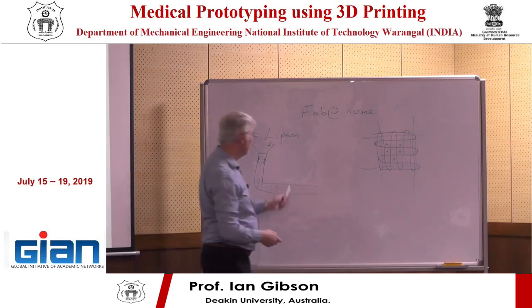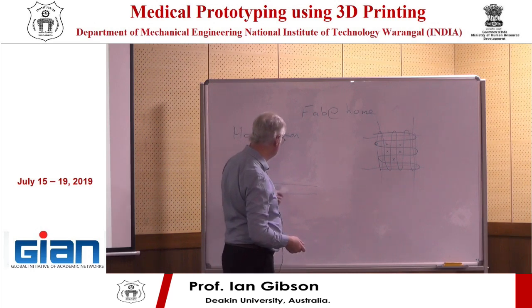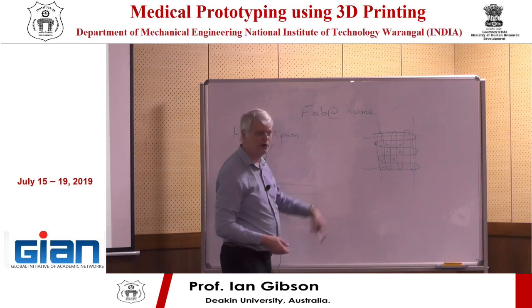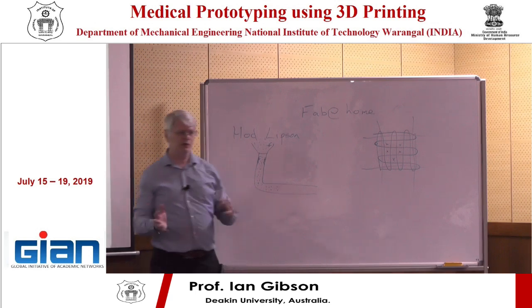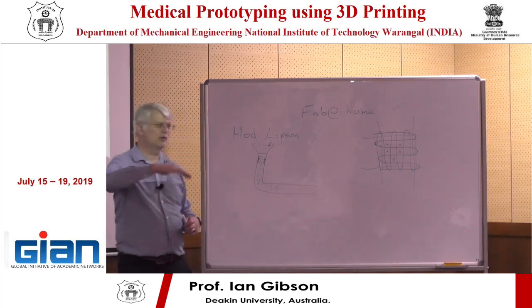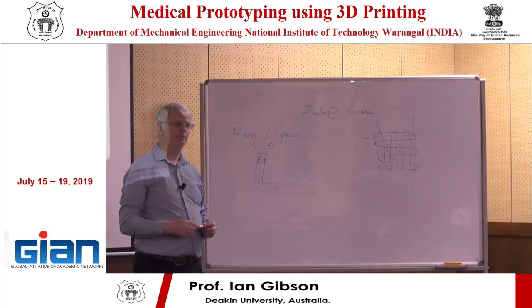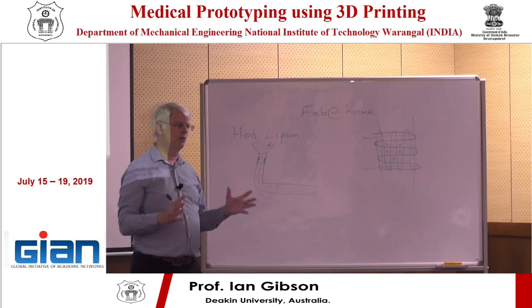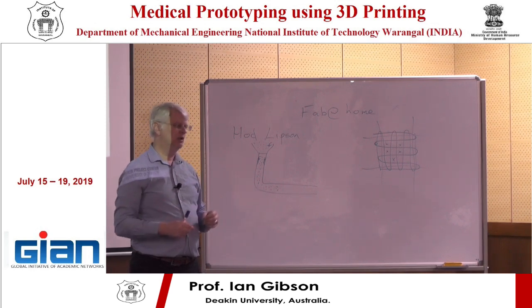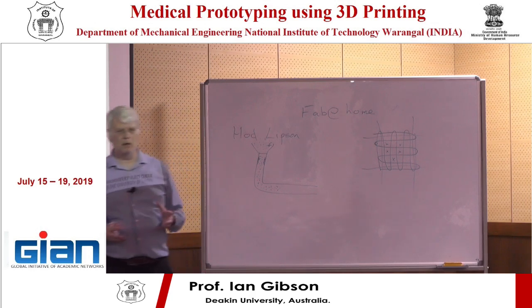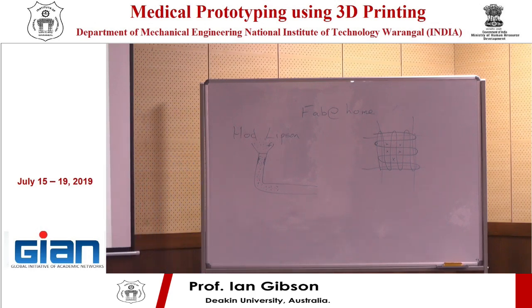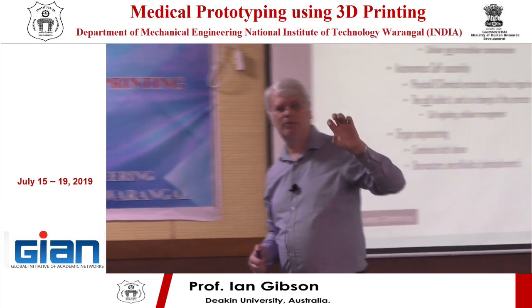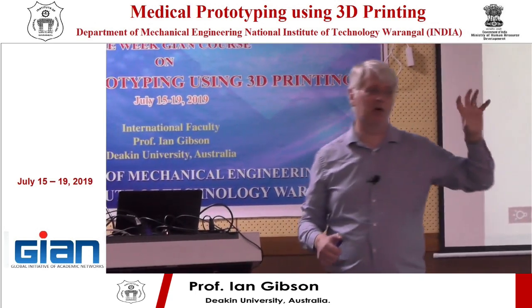So the first thing we did is essentially dissolve our scaffold so that the particles are then exposed. Then we would have a smaller scaffold, pore sizes would be bigger, and those would then have the TCP powders there, and the cells would be able to bond with the powders.